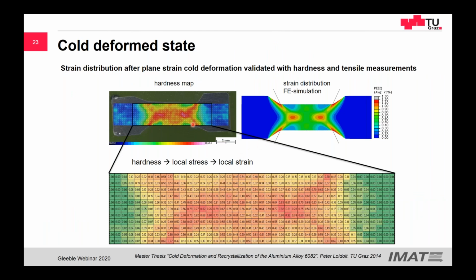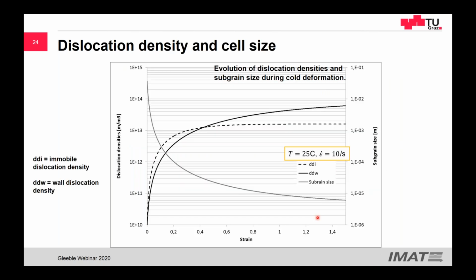So we also try to correlate by a very simple measurement, which is the hardness. They always deliver very nice information. We try to see what happens after the cold deformation during heat treatments. And for this, we first have done a hardness map of the cold deformed part. We calculated the strain distribution with finite element simulations, and with these values we also calculated the local stresses using the flow curves. So here is shown only the local strain, and we could compare more or less this.